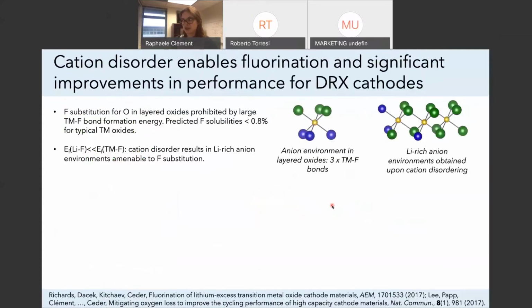One interesting property of these materials, these disordered rocksalt compounds, is that they can incorporate fluorine. So you can substitute a fraction of oxygen by fluorine in these materials, which is something that's not possible in layered oxides. And you can understand this simply by thinking here that your fluorine transition metal bond is much higher in energy than the lithium fluorine bond. And in layered oxides, you need to produce 3 transition metal fluorine bonds per fluorine substitution. Whereas in cation disordered compounds, you can have fluorine sites or anion sites that are almost all surrounded by lithium. So you have these lithium-rich environments, which are the ones where fluorine will substitute for oxygen preferentially.